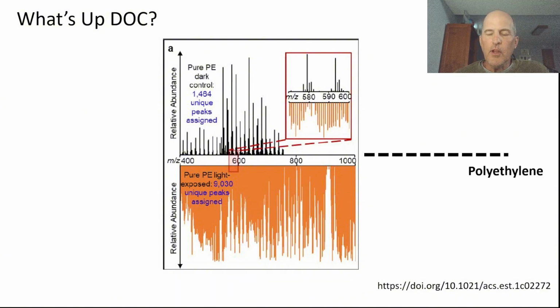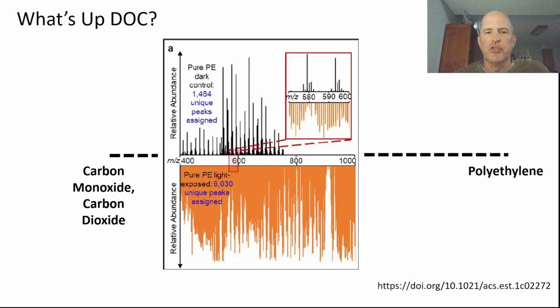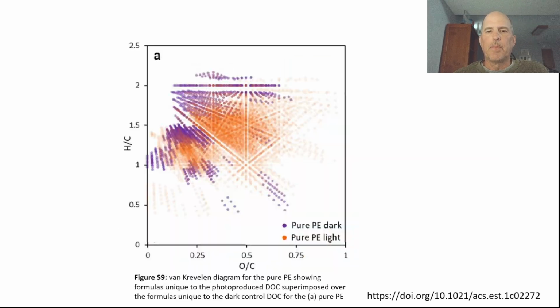So if you were to follow this all the way out to a higher molecular weight, that's where the polyethylene is. That's kind of where you start. If you go to even lower molecular weight, you go to carbon monoxide, carbon dioxide. So you kind of start with something on the right. You see all this stuff in the middle. You're eventually going to get down to the stuff on the left. So the molecular weight is decreasing, the oxygen to carbon ratio is increasing as you get this chemical degradation.